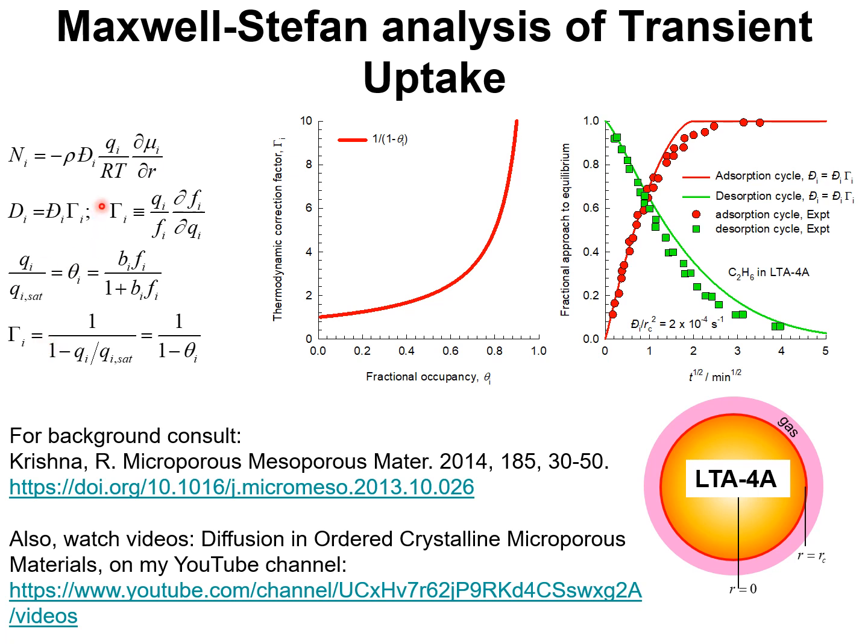If we compare this expression with the Fickian expression shown on the previous slide, we can derive a relation between the Fickian diffusivity D with the Maxwell-Stefan diffusivity Đ, and the relation shows that the Fickian diffusivity equals the Maxwell-Stefan diffusivity times a thermodynamic factor.